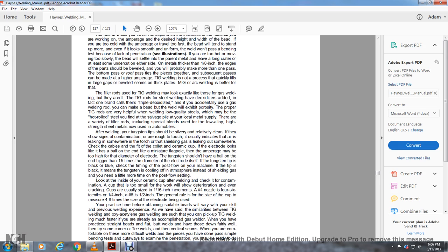There are a variety of filler rods, including special ones using low alloy, high strength sheet metals now used in automobiles. After welding, your tungsten rod should be silvery and relatively clean. If it shows signs of contamination or roughness, that usually indicates that air is leaking in somewhere within the torch, or the shield gas is leaking out somewhere. Check the collet and ceramic cup. If the electrode melts as a ball at the end like a miniature flagpole, then the amperage may be too high for the diameter of the electrode.